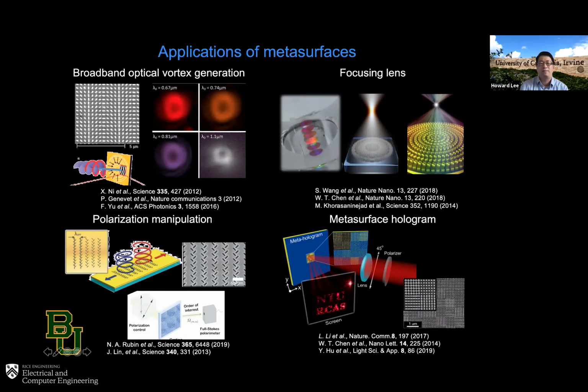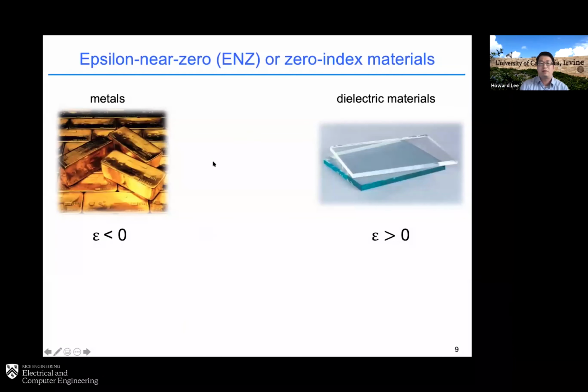So far, this is a patterned nanostructure to create a new phase front so you can control the light interaction here. But another material I want to introduce to you, which has really exciting properties, is the so-called zero index material, or what we call an epsilon-near-zero material. Here epsilon means the permittivity. That means the permittivity is close to zero in this kind of material. Typically your metal has a permittivity below zero in the visible or optical frequency range. And for dielectrics, normally your permittivity is above zero. That's why you have a refractive index of 1.5 in your glasses. And epsilon near zero means this material has permittivity close to zero at a certain frequency.